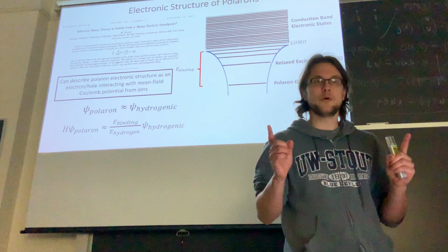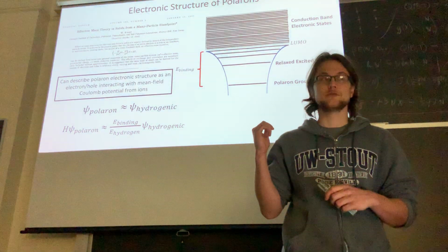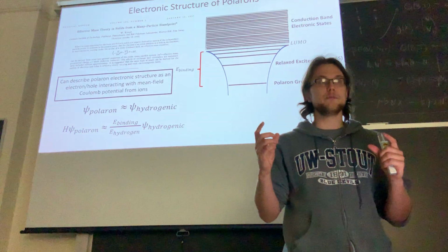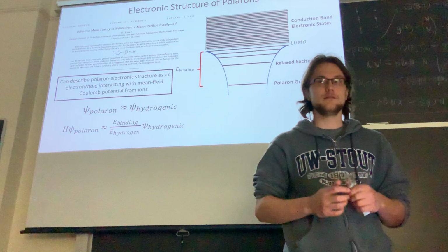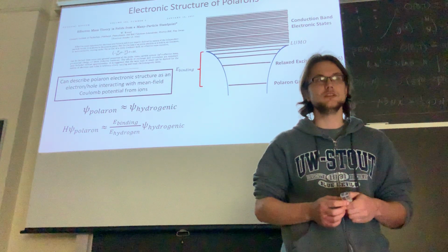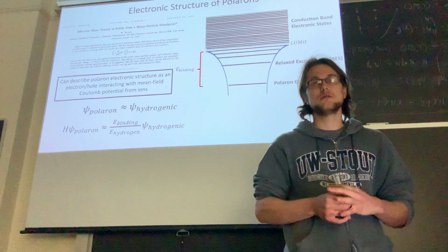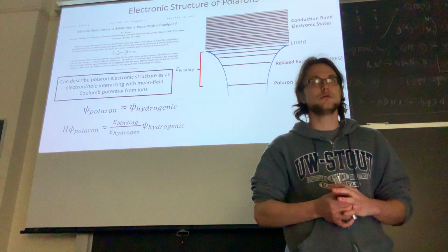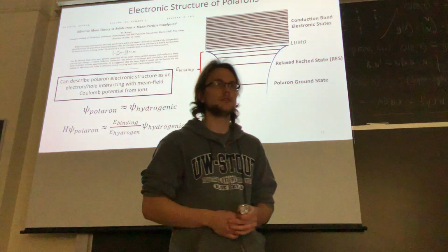And so polarons, you can have a lot of different sizes, so there are different regimes. The ones in these materials, experimentally, we're talking about large polarons, like nine nanometers. So it's not a very bound state, it has a shallower well. And I'm not sure of the exact binding energies, but just from initial computations, it's around 1 eV binding. So it's stronger than a dopant impurity, but it's still less than the hydrogenic. So it's an in-between, essentially.